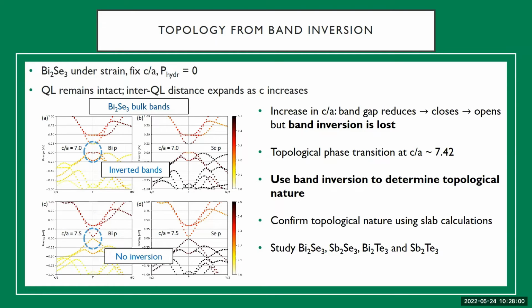So starting off with bismuth selenide, what we did was we fixed the C over A ratio of lattice constants. In the crystal structure, the C axis is along the Z direction, and the A lattice constant is in the plane. And what we're doing is fixing that ratio and relaxing it such that the hydrostatic pressure in the system is minimized or becomes 0. And what we found was that as that particular ratio is increased, which is an equivalent method to applying strain on the system, we found that